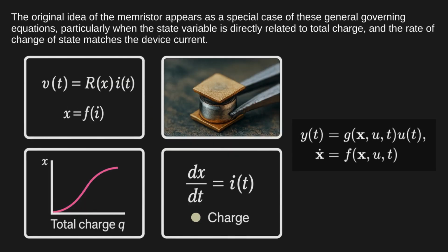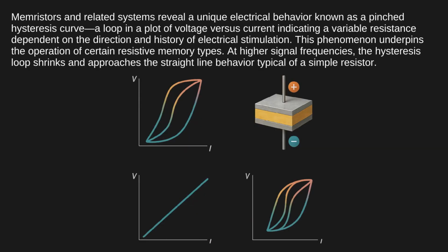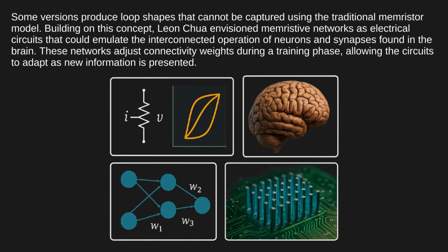The original idea of the memristor appears as a special case of these general governing equations, particularly when the state variable is directly related to total charge, and the rate of change of state matches the device current. Memristors and related systems reveal a unique electrical behavior known as a pinched hysteresis curve, a loop in a plot of voltage versus current indicating a variable resistance dependent on the direction and history of electrical stimulation. This phenomenon underpins the operation of certain resistive memory types. At higher signal frequencies, the hysteresis loop shrinks and approaches the straight-line behavior typical of a simple resistor. Some versions produce loop shapes that cannot be captured using the traditional memristor model.